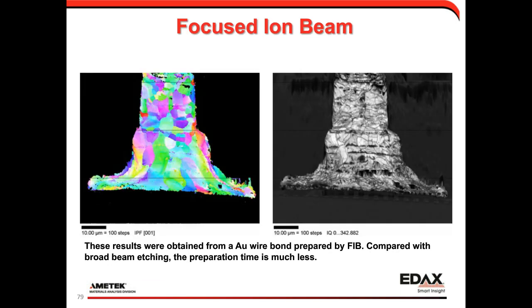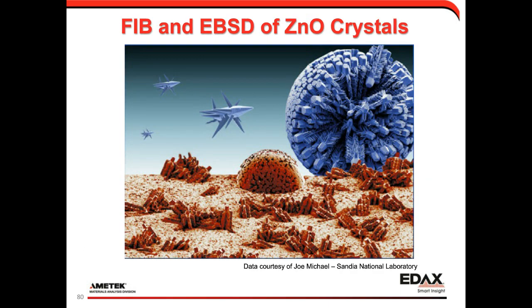So this is just a result I wanted to show to compare to our earlier gold wire bond. This is prepared on a FIB. So we can go in very locally and prepare just that particular area, so the preparation time is less than we'd get with a broad beam source. But with FIBs, we can also go in and do very specific areas on a small scale.